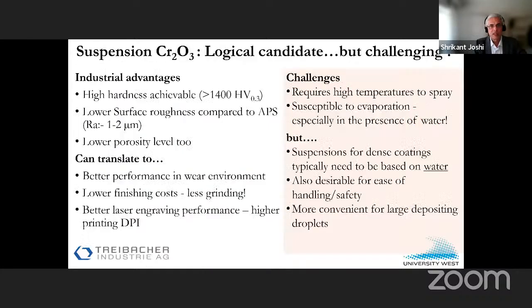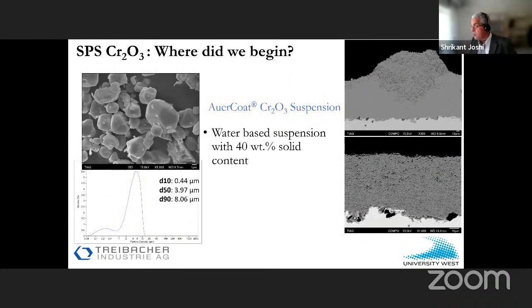wear properties, and that kind of encouraged us to move on to chrome oxide, for example, because this is an interesting material with kind of significant industrial applications. Anilox rolls is a good example. The other reason why it's a good application to target is because we believe that using suspensions can give you a much better as-coated surface, which will reduce the burden on polishing and grinding, which is an absolute must for an application like an Anilox roll, right?